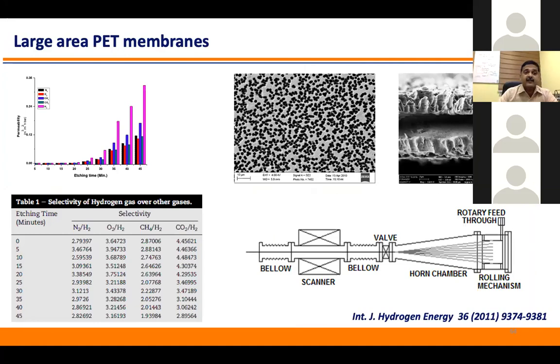This is for the large area that I have shown you, this TIFR setup. So you can see the etching time. When only irradiation has been done, the selectivity of hydrogen over carbon dioxide is 4.4. But as soon as we go to the maximum 45-minute time, the selectivity is 2.89. It means the permeability is increasing with the etching time, but at the same time, selectivity is being lost. Once pores are opened enough, we are not able to control the selective absorption or the selective permeation of a particular gas.